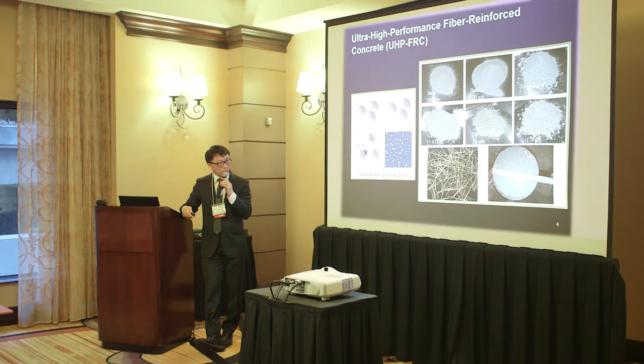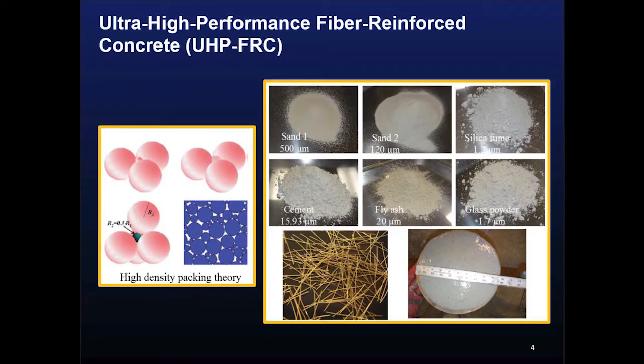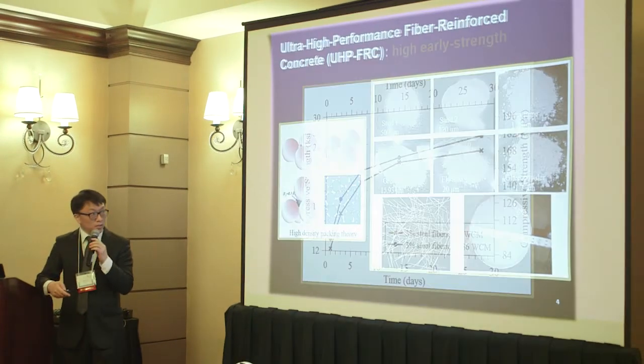So just a quick introduction of UHP-FRC. Basically, UHP-FRC was made by so-called high particle packing density. So we pack different particles, so we can reach a very dense concrete and use less water. That way, we can improve the defects that conventional concrete has. We also add fibers there to increase the ductility. Usually UHP-FRC is highly flowable because of the way we tailor the microstructure.